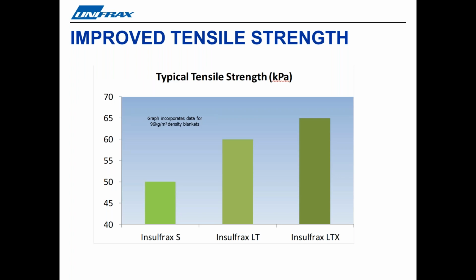The needling of fiber mat during the manufacture generates interlinking of fibers, which provides the blanket with additional tensile strength. So by increasing the number of fibers, we've been able to make the blanket stronger too. Typical tensile strengths have been increased by up to 30% compared with the popular Insulfrax S blanket. Also, with LTX, we have improved on the tensile strength of our Insulfrax LT blankets by up to 10%. The chart here shows typical values for Insulfrax LTX blankets in 96 density compared to Insulfrax S and LT blankets.